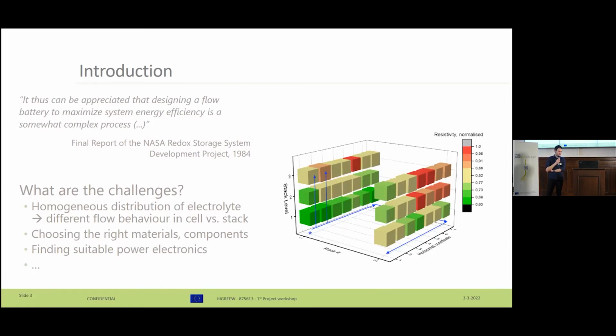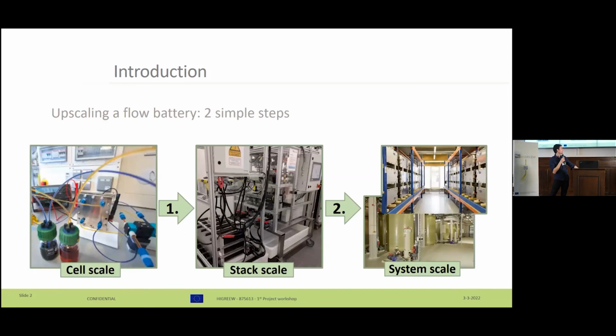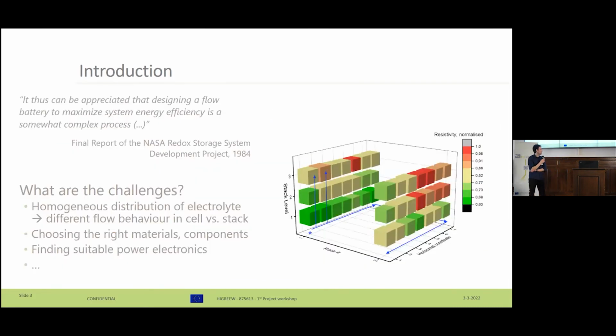And so, for example, in this graph on the right, if you remember the stack shelves on the right, you can actually see here the resistivity inside the individual stacks. If you follow the blue arrows, this is how the electrolyte flows and how it's being distributed in the stacks. And you can see that if you don't supply enough electrolyte, then you will actually starve the stacks in the top rows, and you will have higher resistivity and lower efficiency.